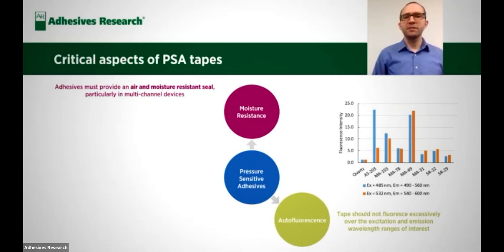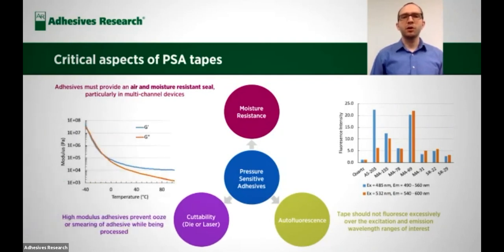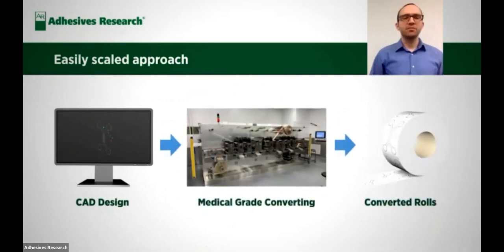Autofluorescence is also very important to keep in mind if you're doing an optical type of test. The tape cannot fluoresce excessively in the region of interest. So we show here numerous adhesives produced by Adhesives Research showing that they have relatively low autofluorescence at some common wavelengths of excitation, 485 nanometers and 532 nanometers. And then finally, the cuttability of the tape is very important. So if you're going through either a plotter cutter or other types of cutting, laser cutting approaches to define your channel, the modulus of the tape is very important to consider, that it's going to cut well, it's not going to smear on the edges, and it's going to make a very well-defined edge for your microfluidic device. And a real advantage of this rapid prototyping using tape approach is that it's also easily scaled.